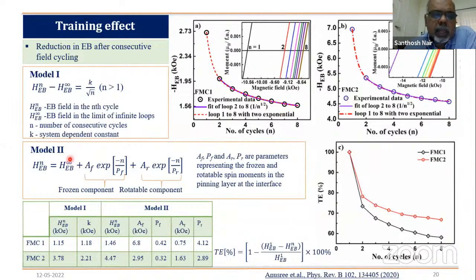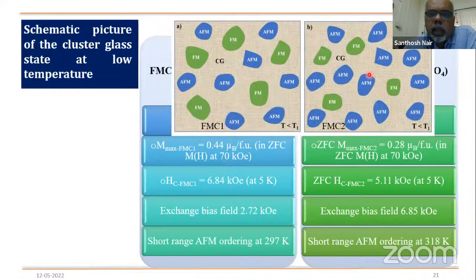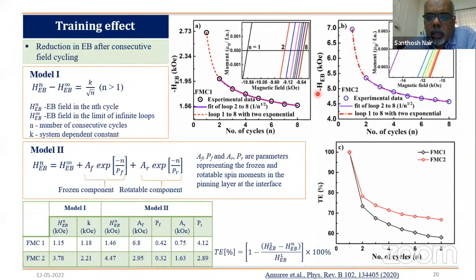We have done exactly the same sort of analysis, and what we find is that the FMC2 sample has stronger antiferromagnetic domains because of the presence of more iron. Iron-iron interactions are fairly strong antiferromagnetic systems. So we have an interface between a large number of antiferromagnetic regions and clustered glass regions that seems to be driving a larger exchange bias. We don't have a local probe to say that this pictorial representation is exactly accurate, but we believe that is the case. This is also published in 2020 in a PRB.